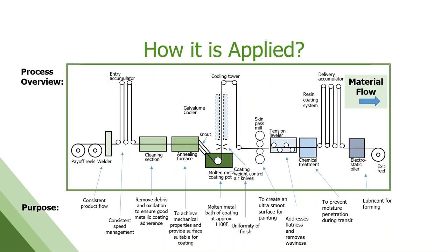This is a diagram of a generic metallic coating line. These lines run continuously anywhere from 150 to 700, 800 feet a minute. So it's a very fast process. It is continuous. We weld the end of one coil to another and keep running. Most metallic coating lines, modern ones, hold anywhere from 2,500 to 5,000 linear feet of steel in them from end to end. So it's a very large scale manufacturing.